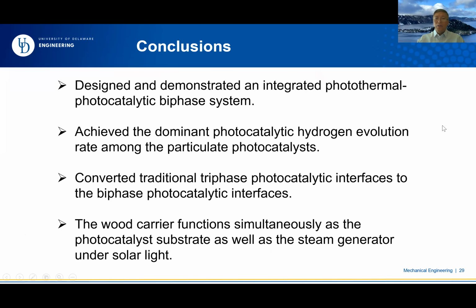All right, so in that case I will conclude here. I hope I've tried to convince you that we have designed and demonstrated the integrated photothermally induced photocatalytic biphase system. And we achieve a quite dominant photocatalytic hydrogen evolution rate among all particulate photocatalyst systems. And we simply regulate the phases by converting traditional triphase interfaces to this biphase interface.